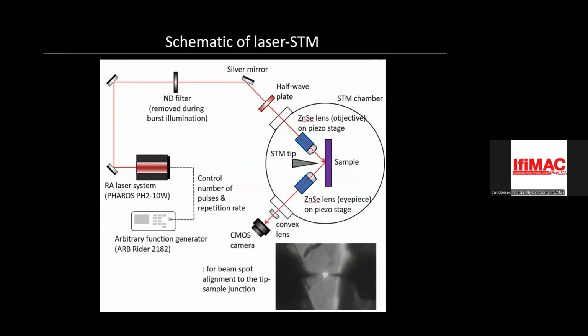The first is we need to be able to focus the light to the tip-sample junction. So that means that in our UHV chamber, you need these lenses to focus. Our lenses are really, really close to the STM tip, a very small distance away. So we can focus the light to 10 microns.